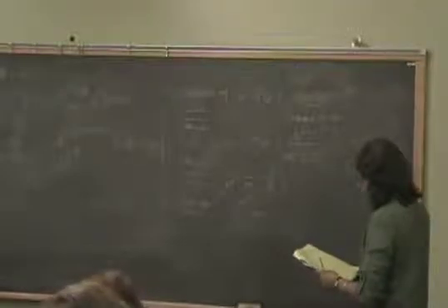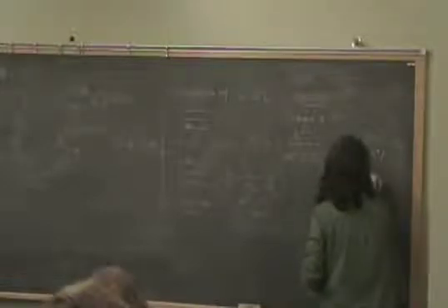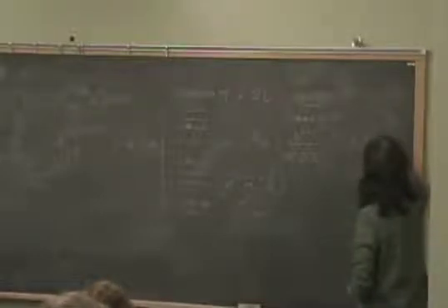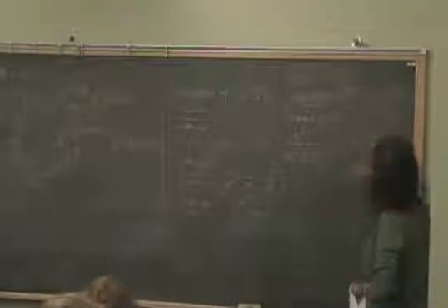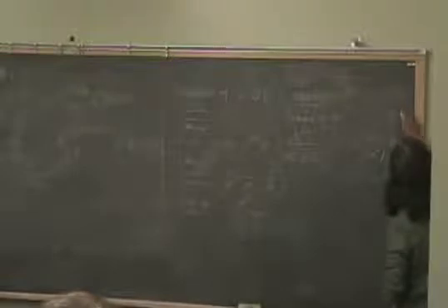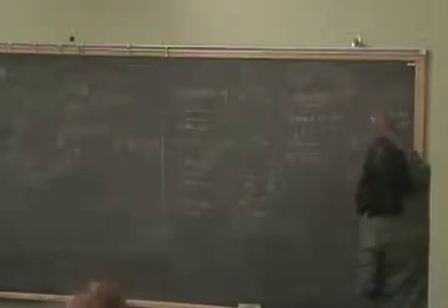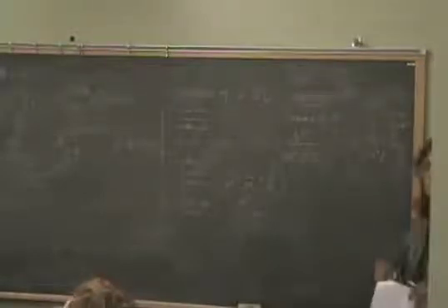Okay, we can just do it here. Epsilon is about 10. Mass is about 0.1, let's say, so it's about 100 times a naught. What is the m in the numerator there? Oh, sorry, this is M0. This is the mass of the electron, just the free electron mass, because I made this the Bohr atom. That's the Bohr radius. So that's the free electron mass. So it's about 100 a naught. So it's a big object.